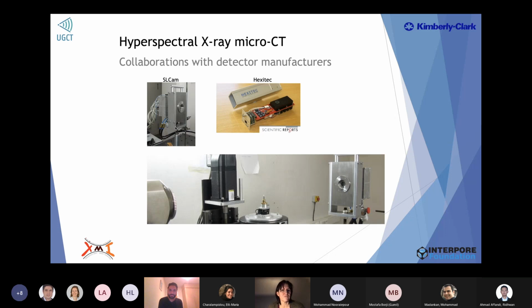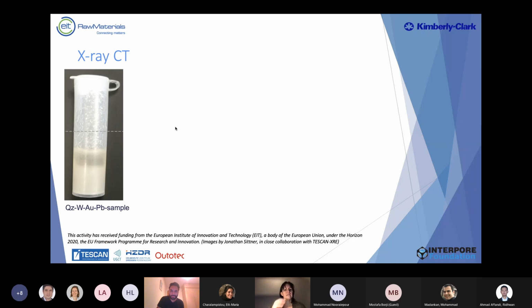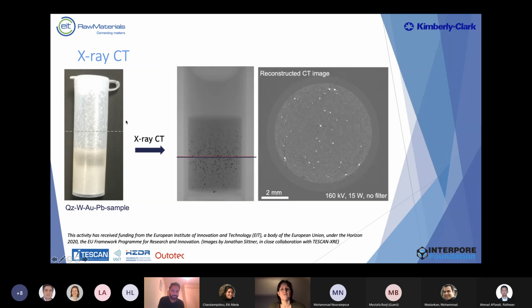We have different hyperspectral detectors, like SLCam, which is sensitive for low energy, and Hexitec, which is more sensitive for high energy. If you have a sample which is a mixture of quartz, tungsten, gold, and lead, and you scan this with normal CT, you see here the radiograph and a reconstruction. You will see bright spots which could be lead, gold, or tungsten, but we don't know which grain we are looking at with just this information.